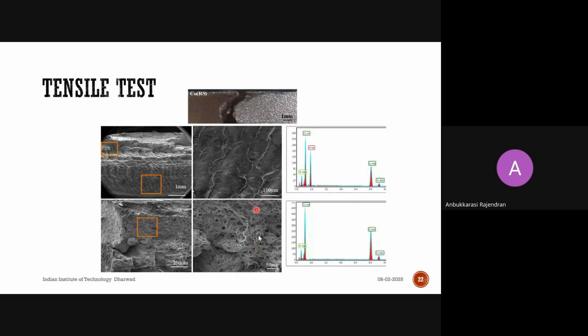So the failure here gives two messages. One is that copper underwent ductile failure, or the ductile failure is happening along the copper region. That was confirmed by the EDS analysis. Another message is that for this you need not do any special sample preparation. Cut the sample as it is, and load it in a vertical position. You can do the SEM analysis as it is in secondary electron mode. Even BSE mode you can choose, in case it is some composite with particles or intermetallics you are expecting at the interface.